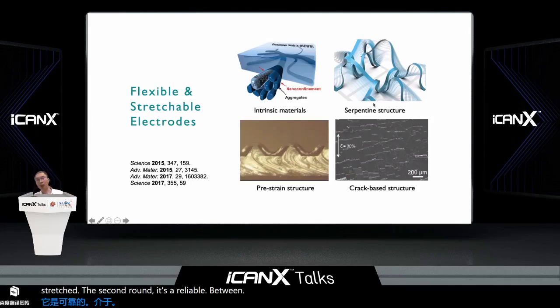This was developed by John Rogers' group. It's called a serpentine structure. They first brought in a ribbon structure, a silicon ribbon, an inorganic material, that can bend and stretch and be linear, but without continuous conductivity. There are also other approaches like the pre-strain structure, crack-based structure, and so on. People can refer to all these papers.